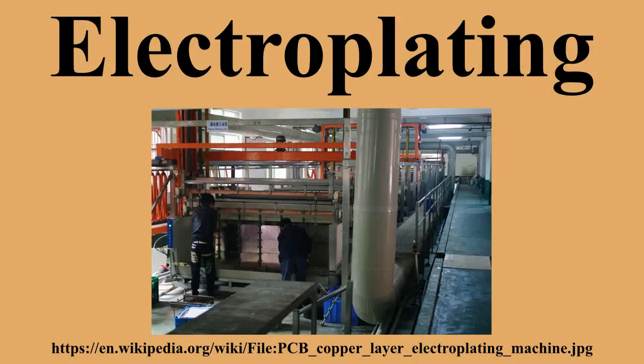This shape allows one to place the test panel at an angle to the anode. As a result, the deposit is plated at different current densities, which can be measured with a Hull cell ruler. The solution volume allows for a quantitative optimization of additive concentration. 2 gram addition to 267 milliliters is equivalent to 0.5 ounces per gallon in the plating tank.